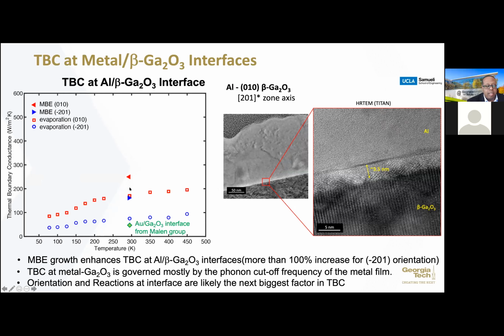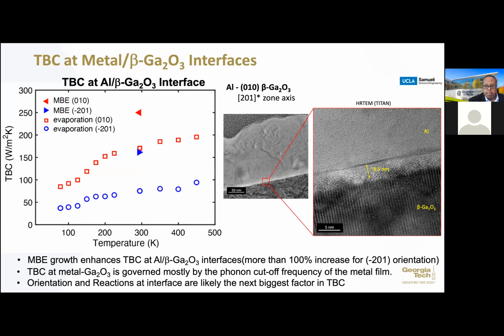And part of this, we're looking at the chemistry at the interface of how the metal's interacting with materials like beta gallium oxide. It's not just beta gallium oxide. We've seen this with other materials as well, depending on how we're depositing it and increasing the thermal boundary conductance. But here with beta gallium oxide, you start getting these interfacial reactions. And so again, as you try to do this, how do you control these reactions in order to maximize the thermal boundary conductance on these particular structures?